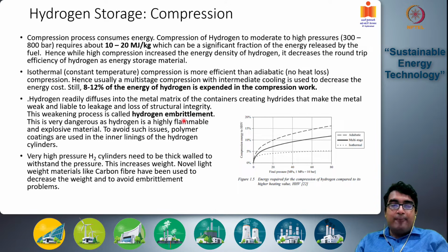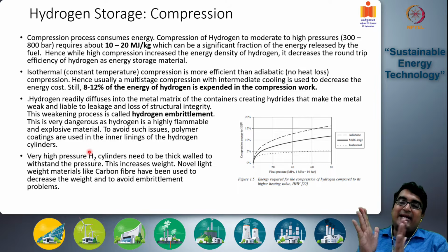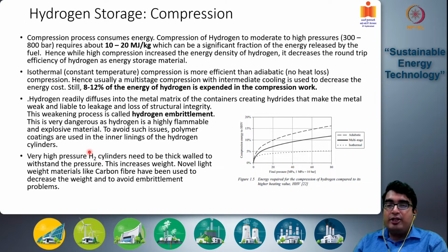So this weakening process is called hydrogen embrittlement and is a significant problem in the handling of hydrogen. This is very dangerous as hydrogen is highly flammable and an explosive material. To avoid such issues, polymer coatings are often used in the inner linings of hydrogen cylinders, which can act as barriers to hydrogen diffusion. There is a lot of research going on in developing better coatings that can further decrease this hydrogen embrittlement problem in the high pressure cylinders.